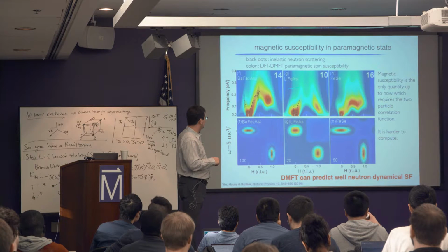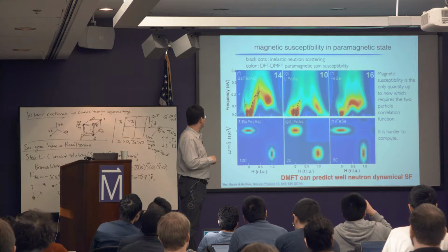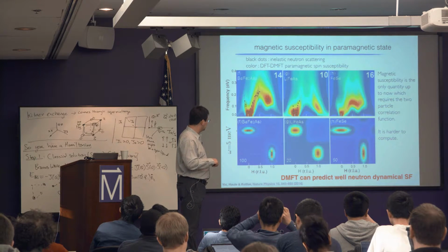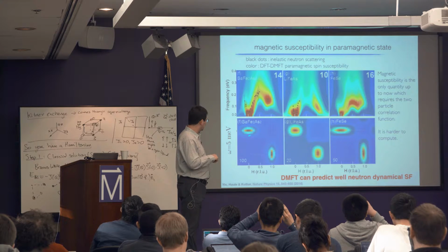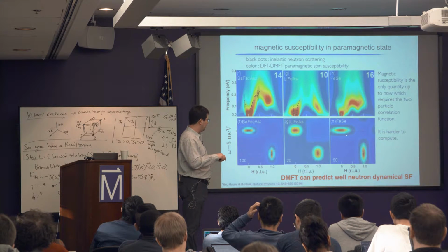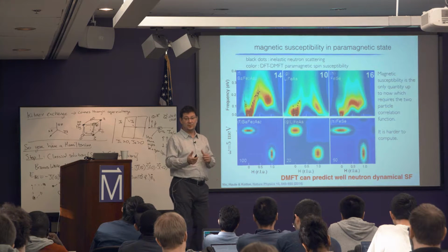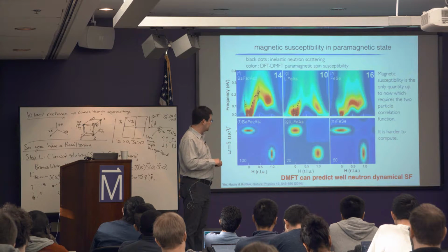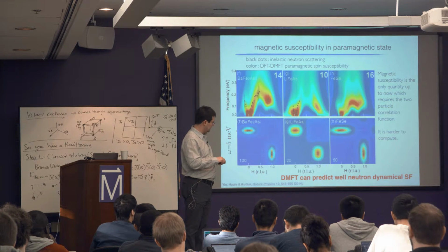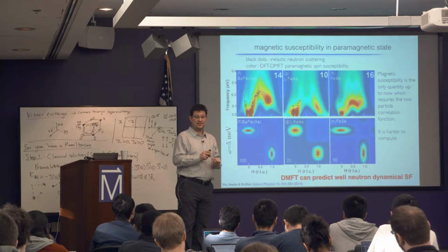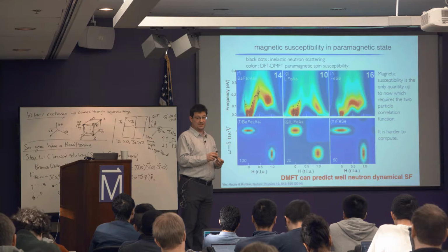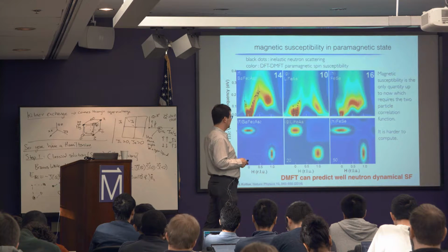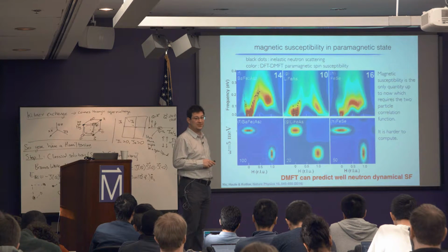And here are examples for iron superconductors. So BaFe2As2, LiFeAs, FeSe. And the important point is that what happens in these superconductors is that they have this pretty large blob of spectra near (pi, 0), (0, pi). Why? Because they're close to a magnetic instability. But nevertheless, if this intensity here is not extremely sharply peaked, they will not go through the magnetic transition, because this becomes very strong, but not strong enough to go to the ordered phase. And many times it shifts a little bit to incommensurate Q.